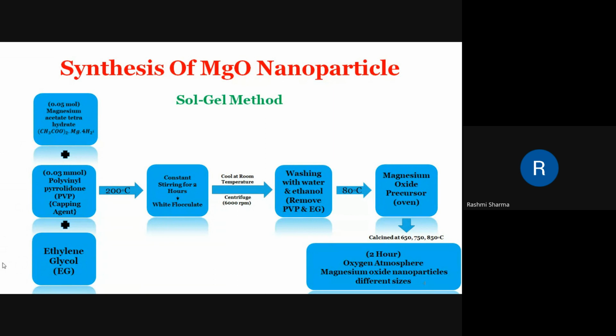This flocculate was cooled at room temperature, and then centrifuged at 6,000 rpm. After centrifuging, it is washed with distilled water and ethanol in order to remove the remaining PVP, polyvinyl pyrrolidone, and ethylene glycol. The final drying of the flocculate was done at 80 degrees Celsius to get a magnesium oxide precursor. After we get the precursor, it is calcined at 650, 750 and 850 degrees Celsius respectively for 2 hours in oxygen atmosphere to get magnesium oxide nanoparticles of different sizes. So using this sol-gel method, we can get nanoparticles of different sizes.